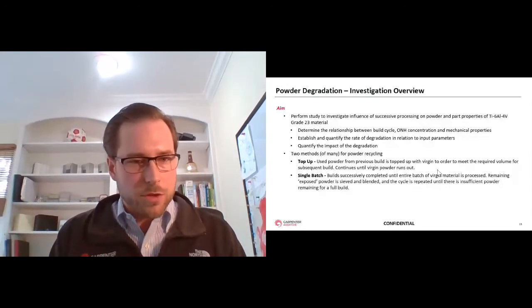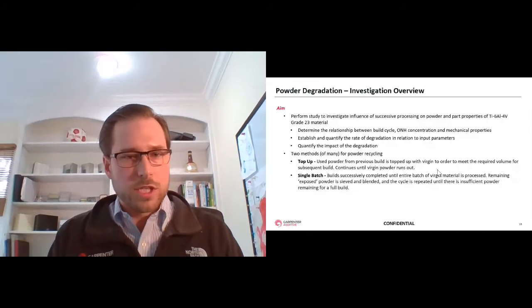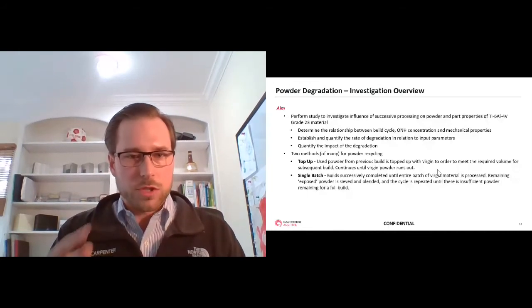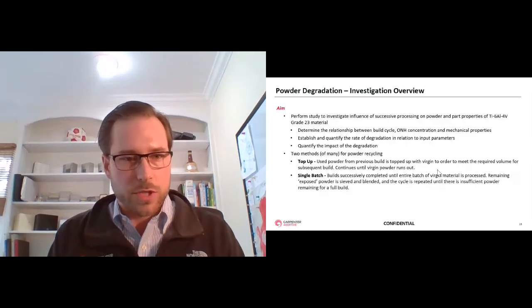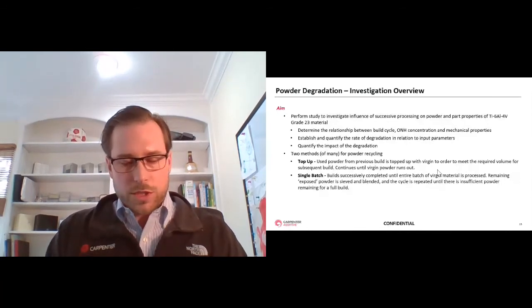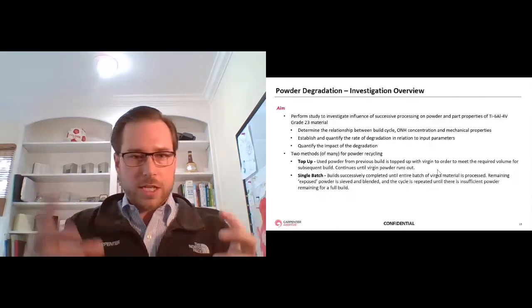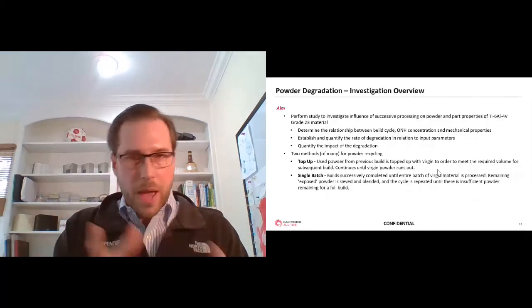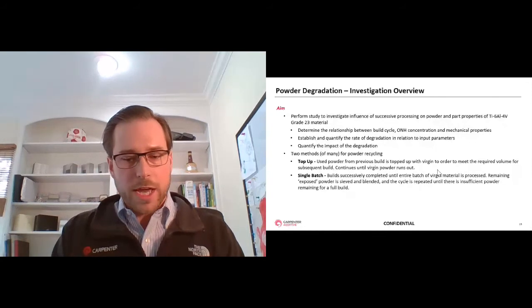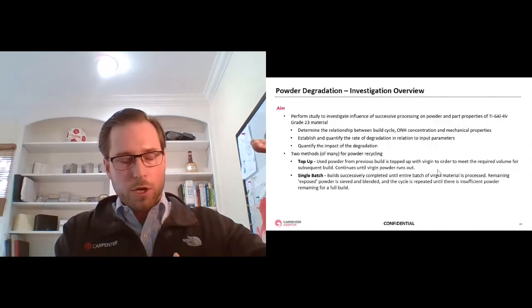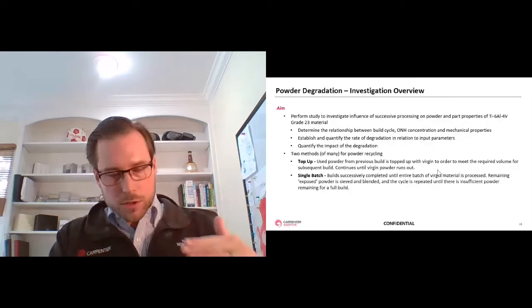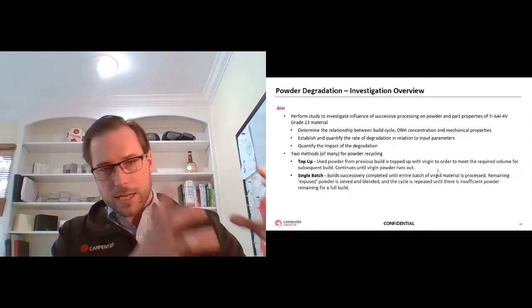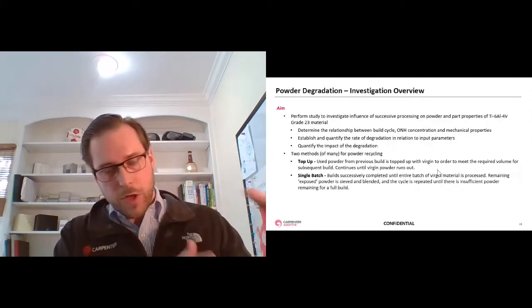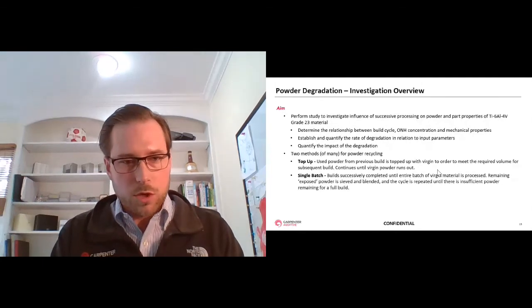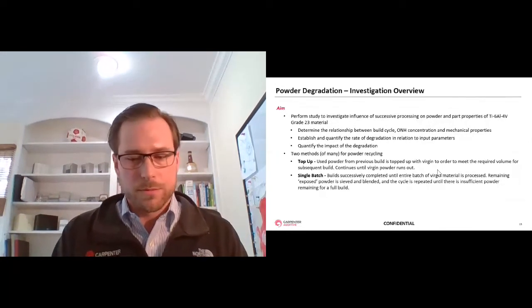And the second methodology is single batch. So this is where we complete builds successively until the entire batch of virgin material is processed. So once it's processed, all that exposed powder is sieved and blended, and it's put back into the machine. So you might fill up a build hopper, you might do 3 builds before you take that whole batch out, recycle it, and put that whole batch in, and then that's one exposure of powder.